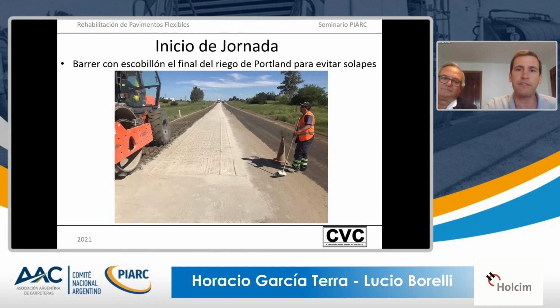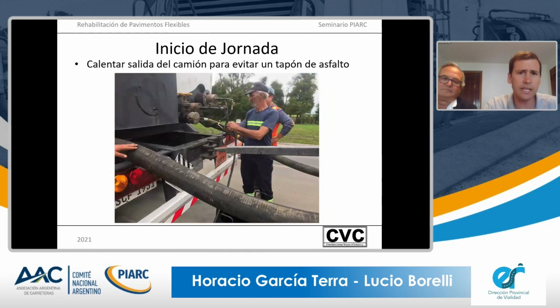Once we laid the Portland cement and we swept the Portland cement, and if you are not doing a lap, you are including 2%, and you may find out in time a transverse cracking. That's why you need to sweep.